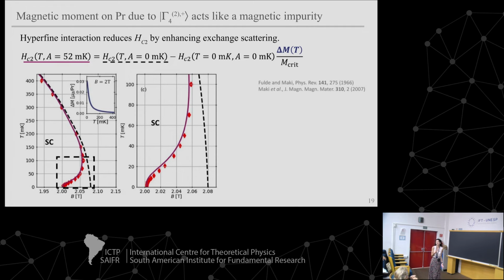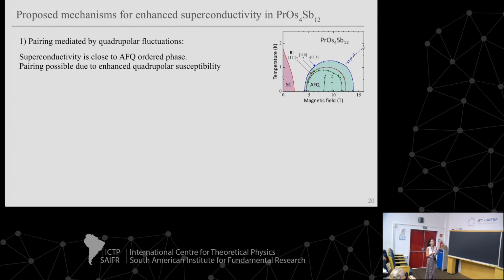So we think that this nicely explains what's going on. It's not exotic or anything like that. You're simply adding magnetic impurities and you're breaking the Cooper pairs. Quantitatively, the saturation is also nicely matched and everything is good here. So apart from being a nice fit to the data, can it really tell us something useful about the superconductivity? We think that the answer is yes.